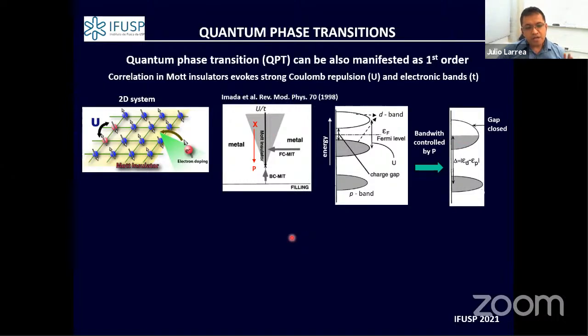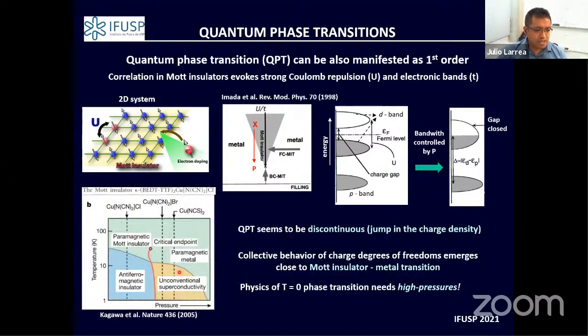But this is not only a theoretical prediction. In fact, one can observe this in a synthesized material—a molecular material that shows this 2D Mott Insulator state. What you observe is that you can pass, even at almost very low temperature, defining a quantum phase transition from a Mott Insulator to a metal.